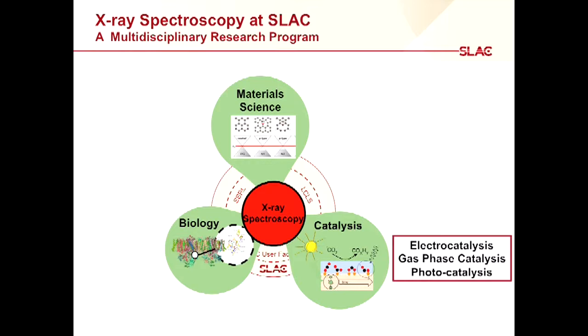And something I will emphasize even a little further is that we need to design the experiment in a way that is also appropriate for the X-rays. Hard X-rays are mostly bulk sensitive. So once we have a sample on the order of micrometers, and we are after a very specific element, let's say iron or copper, X-rays will necessarily probe all those atomic species that are there. They provide cumulative information that is the superposition of all the potentially different species of the same atom that coexist in the sample. So when designing catalytic experiments, it's really important to make sure we have materials that actually participate in the reaction, and not something that is just sitting there without participating.